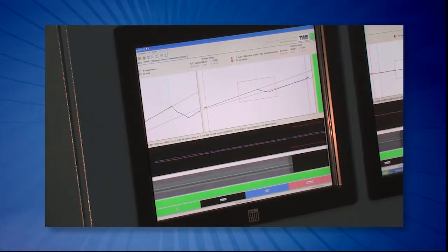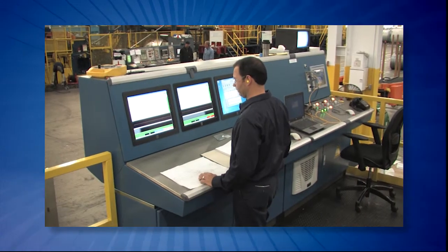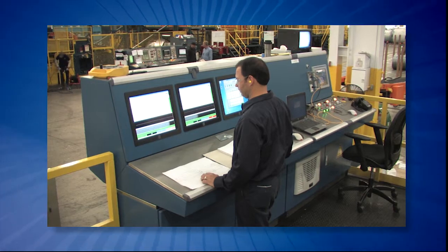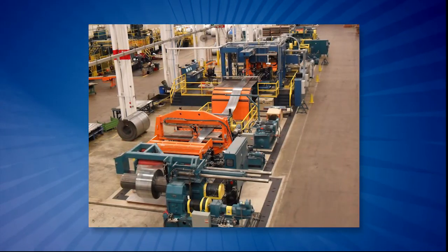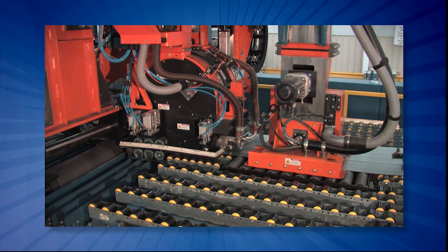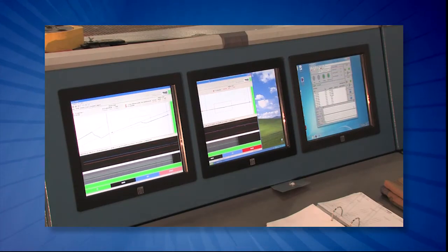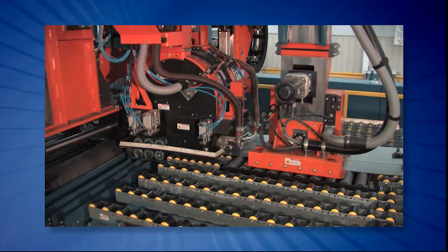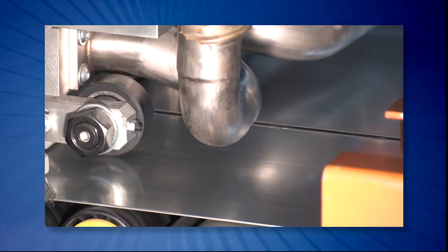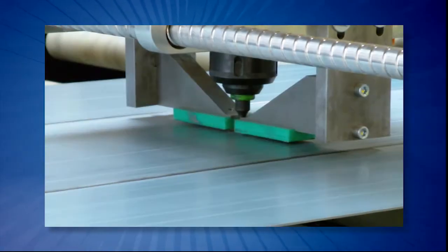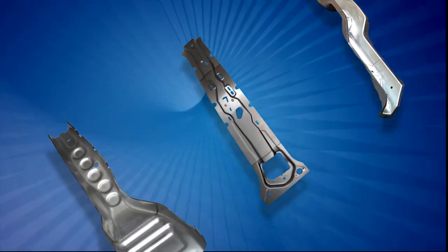During the welding process, the weld seam is monitored for quality assurance and reliability using TWB's proprietary magnetic flux leakage detection system, along with top and bottom seam profile monitoring systems. Any defects detected are identified on the coil with a paint marking and/or a punched hole that can automatically be sensed during the stamping or forming process.